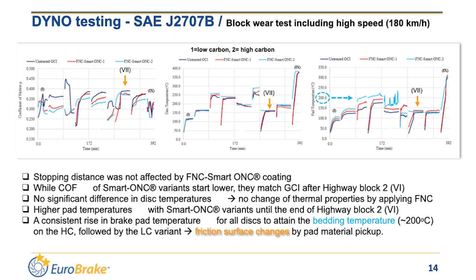And there is a consistent rise of pad temperature to achieve the bedding temperature at about 200 centigrade. It was achieved first for the high carbon one and then for the low carbon one, which indicates a change in the surface friction by the pad material pickup.